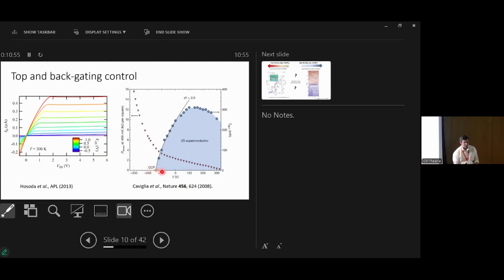Actually, it turns out to be not so easy, because the mobility, the scattering in the system, is changing consistently as you deplete the electrons away. So this wasn't quite so clear as they initially wanted. But still, it's a really beautiful example of tuning a material with a parameter which we don't always have access to. You can't do this with a metal, for example, because the carrier density is too high.